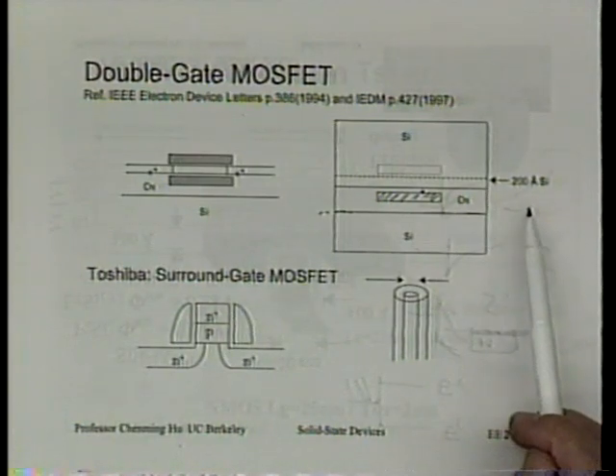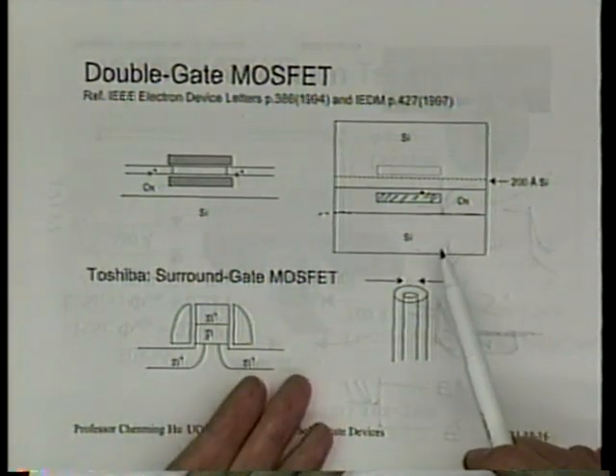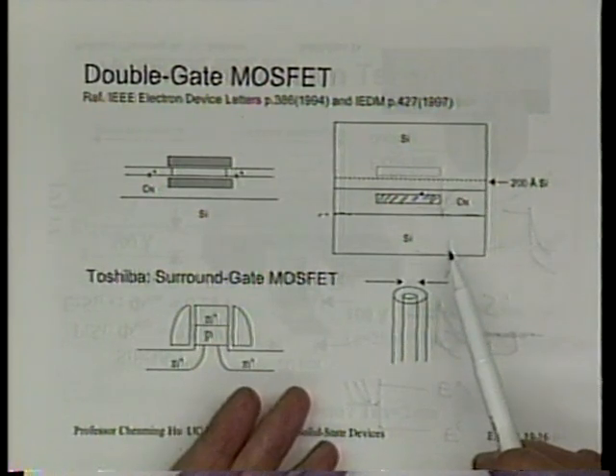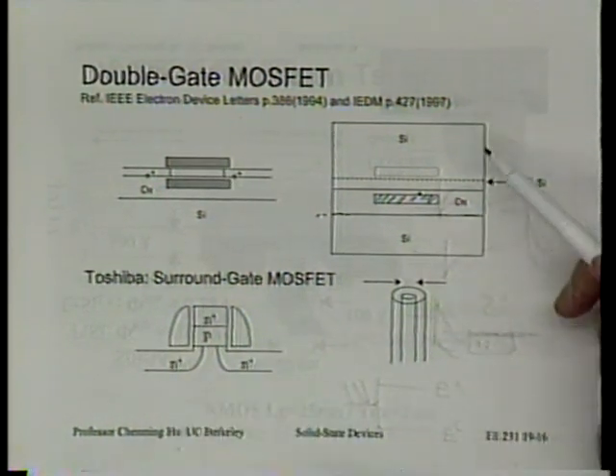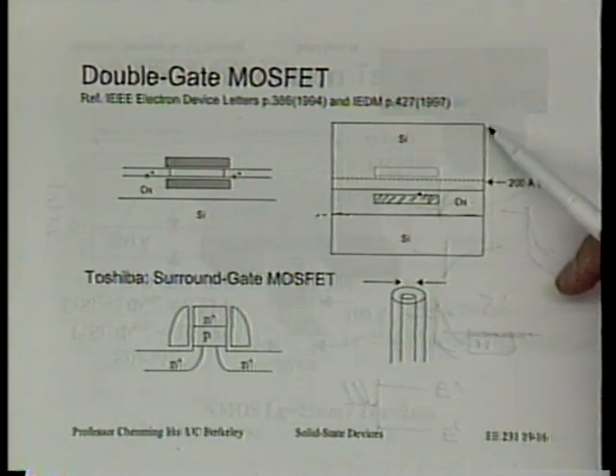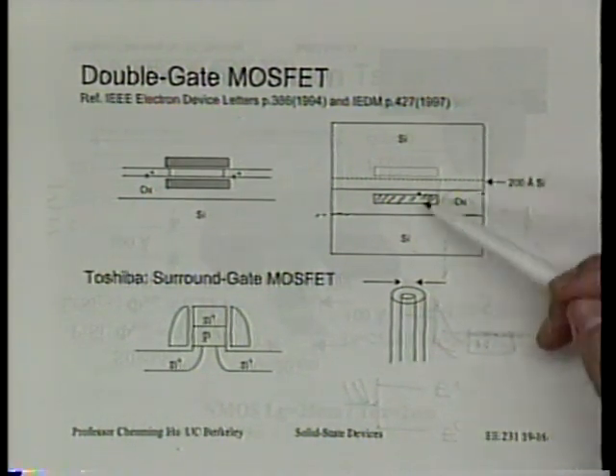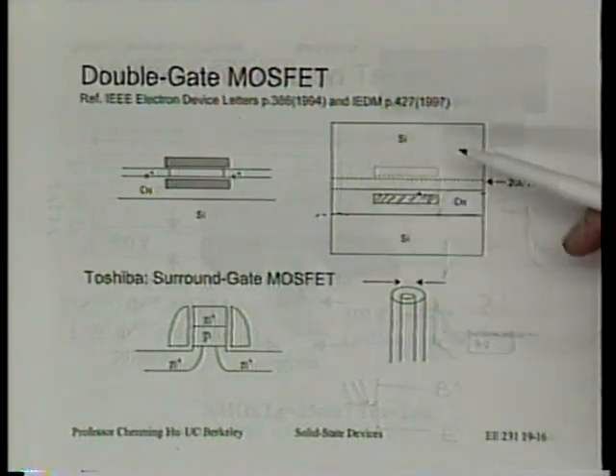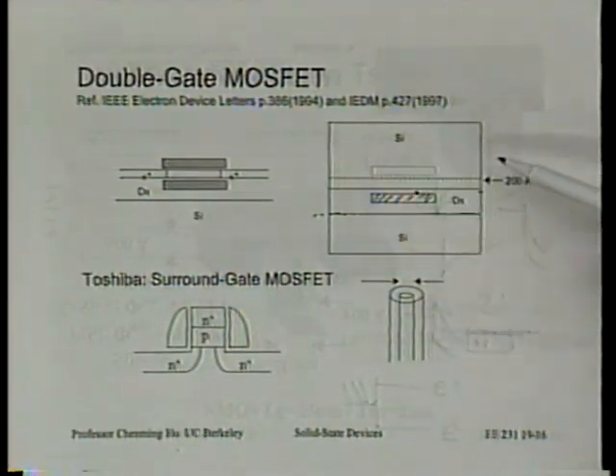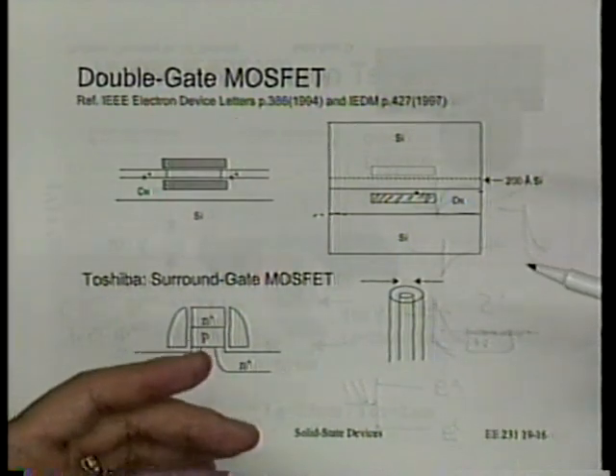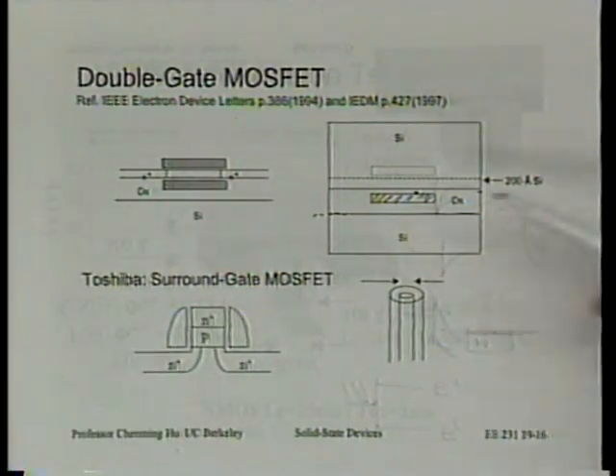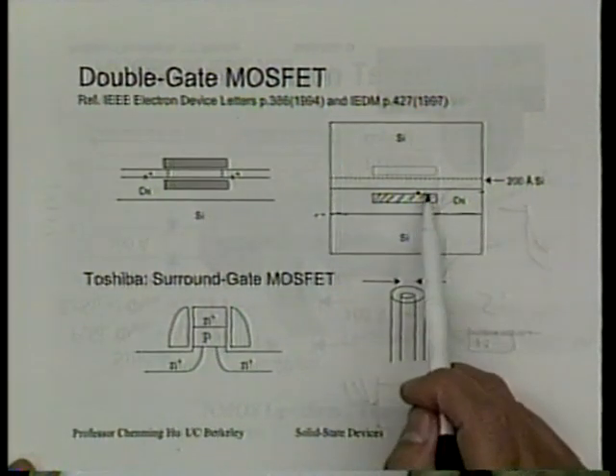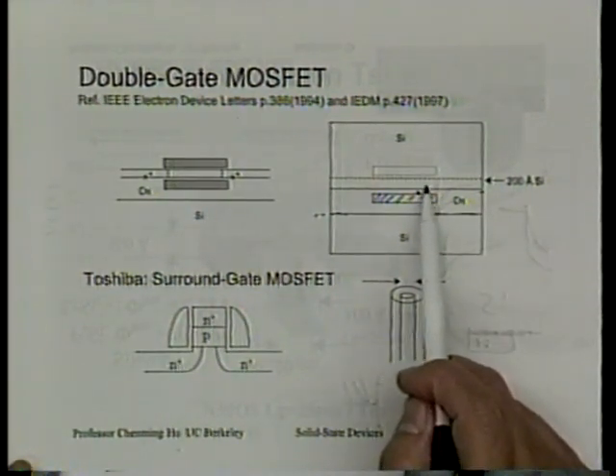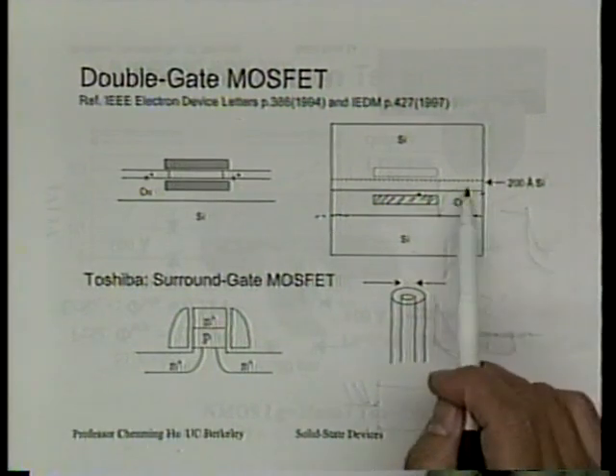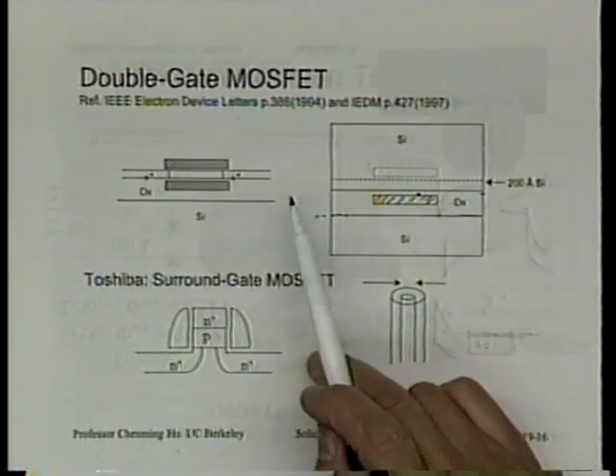All right. After that, you bond it with another silicon wafer. Is it okay? After that, you start etching away the top silicon. Remember, the silicon is still here. There's no dotted lines yet, right? You start etching this away as if you're making SOI material using a wafer bonding technique. So after you etch this way and are left with the thin silicon film, until you have 200 angstrom silicon film left. All right? Now you have SOI now.